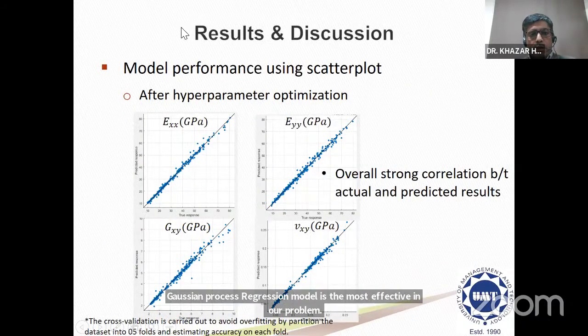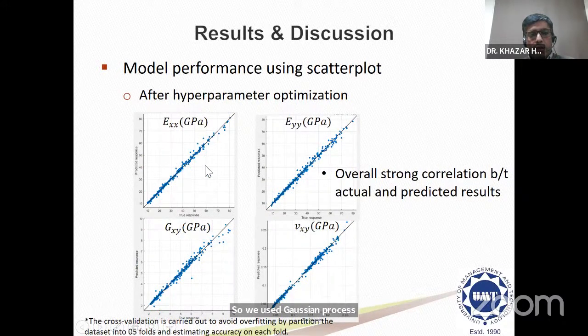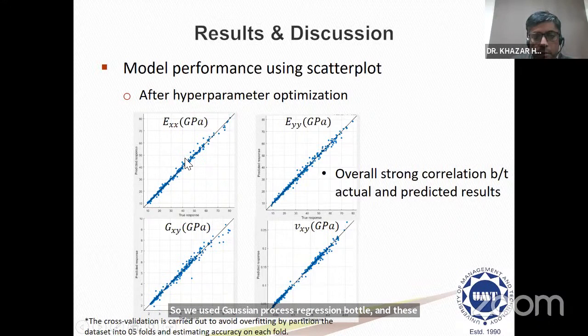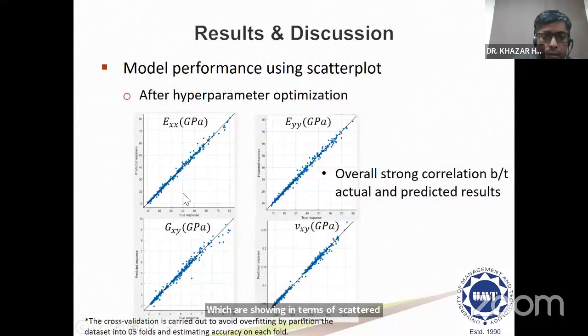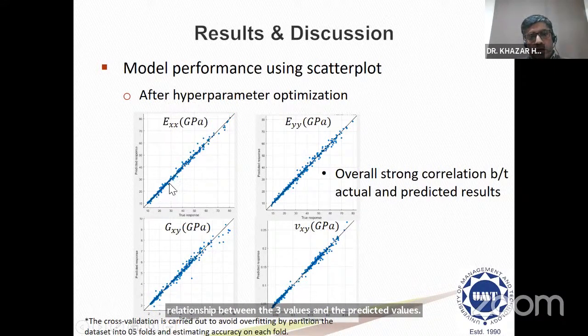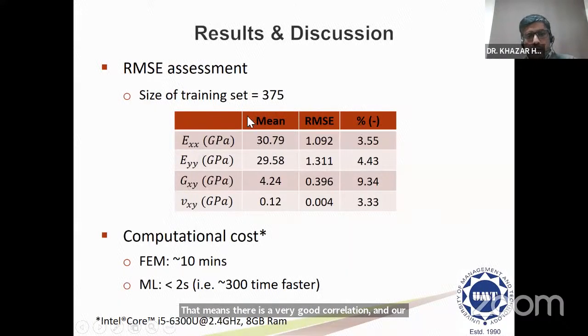So we used the Gaussian process regression model, and these are the results, shown in terms of a scatter plot. The relationship between the true values and the predicted values, and as you can see, all the data is very close to the diagonal line. That means there is a very good correlation, and our model predictions are quite accurate. So in terms of numbers, you can see that except in-plane shear stiffness, for other stiffness values, we have a reasonable agreement.